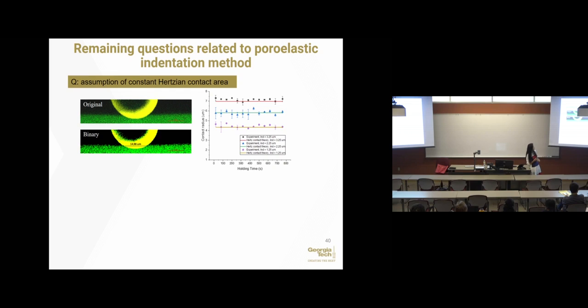So you can see this is the indenter, this is the gel. We can measure the contact radius as a function of holding time. You can see this straight line is from a Hertzian solution, which is the no-adhesion solution. And they compare with this theoretical value very well. So actually, this adhesion between hydrogel and indenter is very weak because 90% of the gel is water. It doesn't influence the characterization.